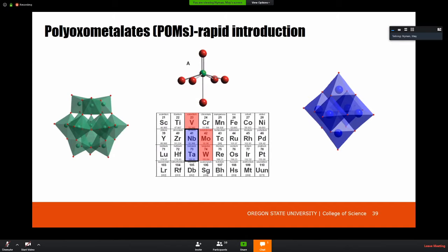Okay, but here we've got simple solutions. We don't have anything fancy like copper amines. So we had a hypothesis that what's forming is this Nb24 ring. And so we simulated some scattering data of linking these Nb24 rings together with different alkalis. Here we've got 2 of these Nb24 rings linked together with lithium. That's the simulated scattering data. It fits very nicely with the experimental scattering data in red. So we're pretty confident this is what's happening.